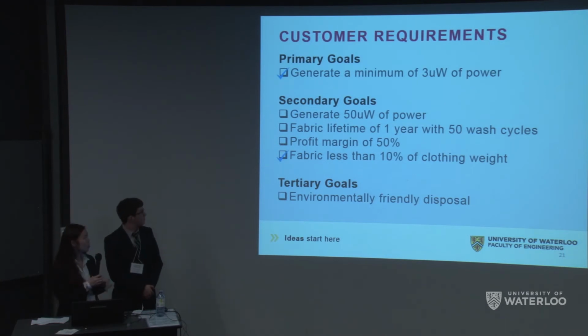A goal that we think could be achieved, but we didn't have time to test, is the fabric lifetime of 1 year of 50 wash cycles, because you would never wash the film, so you would expect a standard piece of cotton fabric to be able to survive that. So we essentially didn't test that just due to time constraints, but we believe it could be met. And the goals we didn't meet were environmentally friendly disposal, 50 microwatts of power, and a profit margin of 50%, as the film is kind of expensive.